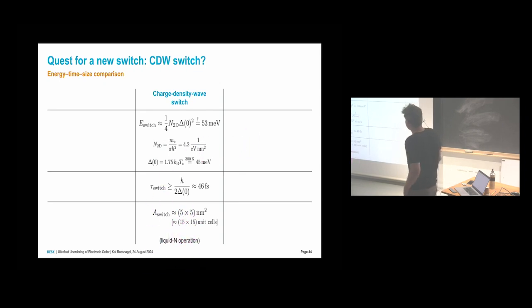Yeah, it should operate at liquid nitrogen temperature, which is not so good. But let's say, conceptually, the switching energy would be this condensation energy. If I go with a 2D system and take the density of states of the 2D electron gas here, and if I go with a mean field type transition with 300 Kelvin transition temperature, this is the gap size. This would give us 53 millivolts switching energy and a time scale of 46 femtoseconds. And I would say you need about 15 atoms square, 15 unit cells, so that you have a developed band structure, and maybe you can speak of something like a band.